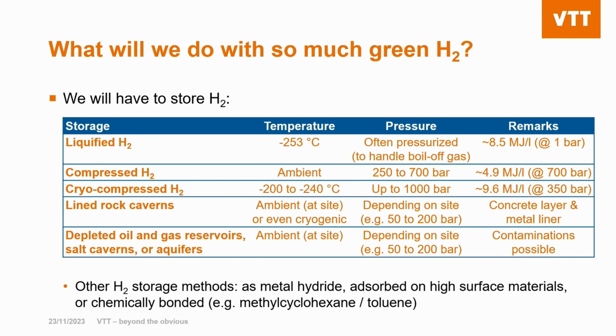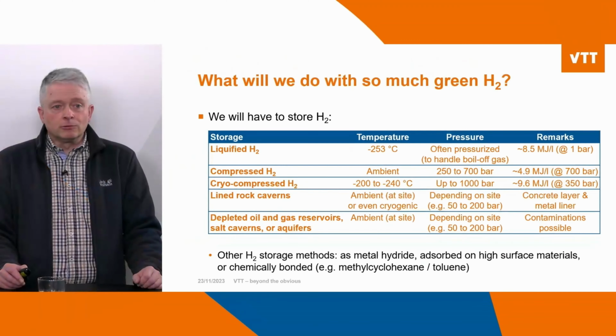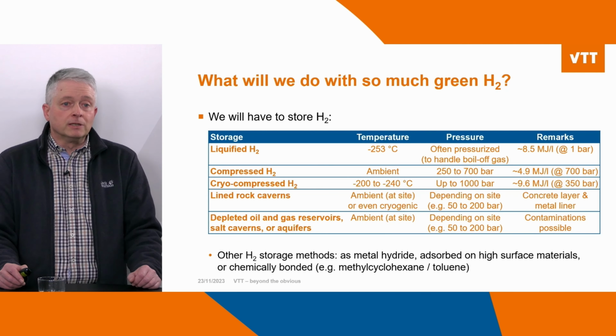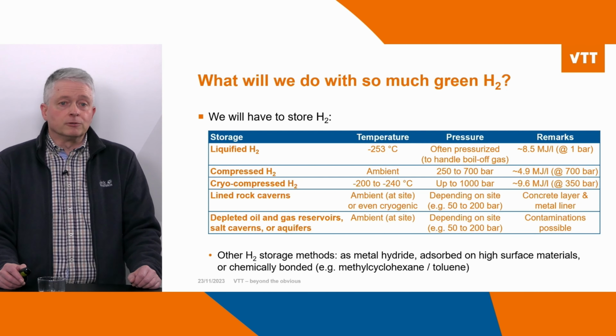First of all, we have to store it. We can do that as liquid hydrogen. Then we have low temperatures, about minus 250 degrees Celsius or even lower, and the pressure is relatively low. It's also possible to store hydrogen only compressed. That is possible at ambient conditions. And also a combination, cryo-compressed hydrogen, where we have minus 200 to minus 240 degrees Celsius and up to 1,000 bars. And we get then the highest volumetric energy density.